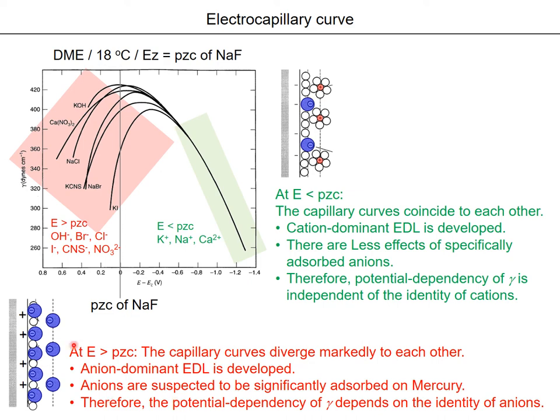And also, on the surface of the electrode, you have a lot of anions, which are specifically adsorbed on the surface. Anions are suspected to be significantly adsorbed on mercury. So because of this kind of non-ideality, the potential dependency of the surface tension depends on the identity of the anions. Sometimes chloride ions are adsorbed, sometimes hydroxide ions, sometimes nitrate ions, and the situation becomes different for each anion. So you have various capillary curves in this region of potential, depending on the anions.